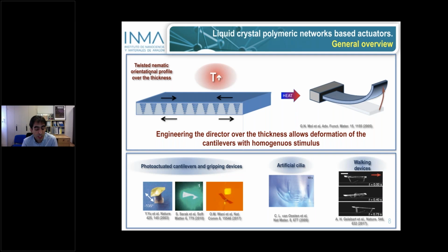Using this principle of deformation and controlling the morphology, that is the orientation of the molecules, we can implement controlled deformation. As a typical example that is ubiquitous in the literature, here you have a cantilever in which the molecules lie parallel to the surfaces of the cantilever, but their orientation is orthogonal in one side with respect to the other side. So if we heat this cantilever, the material tries to contract in the preferential direction of the molecule. So the upper part of the cantilever tries to contract in the direction indicated in the cartoon. But in the bottom part, due to the orientation of the molecules, the system tries to expand in this direction, and the system, to accommodate these stresses, goes out of the plane and bends upwards.